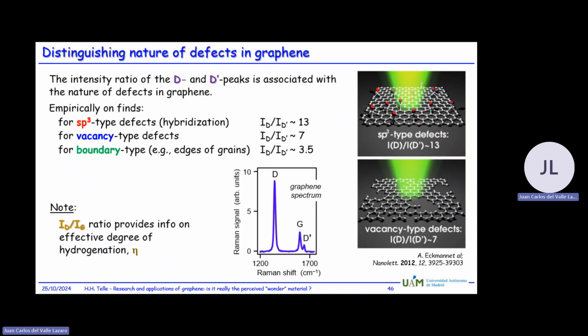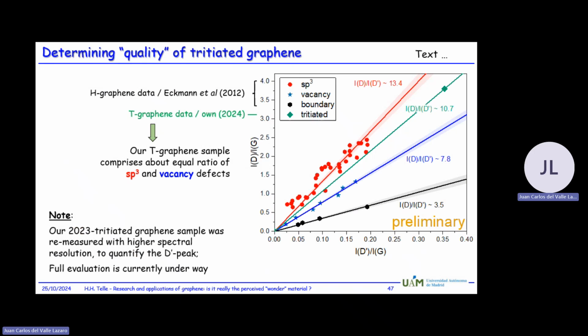You can also tell something about whether there are molecules attached or not, whether it's a smooth or a ragged boundary. So basically, if you look at that information and plot the two ratios with respect to each other, you find that, for example, for one type of damage, you get a slope between these two ratios which favors the sp3, and another slope where you only have mechanical damage. And we actually looked at our tritium samples, and at the moment, or when this was produced, there were only preliminary results. We had only one data point at that moment. In the meantime, it's much more.